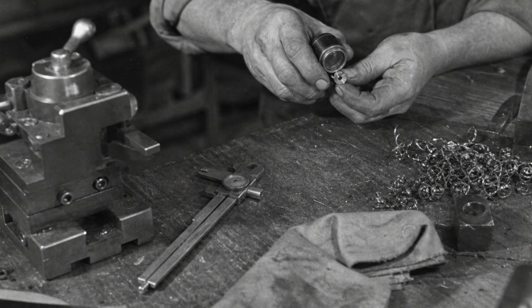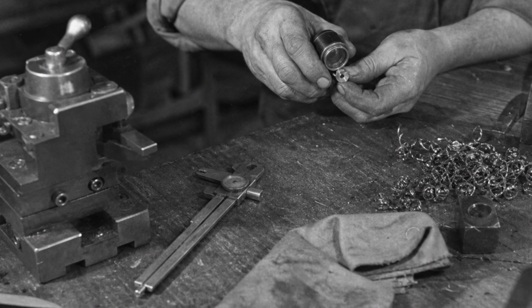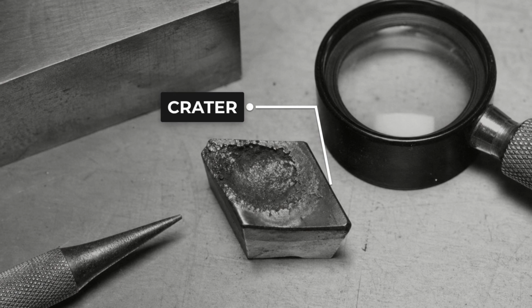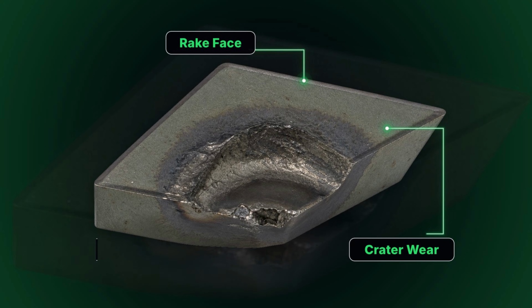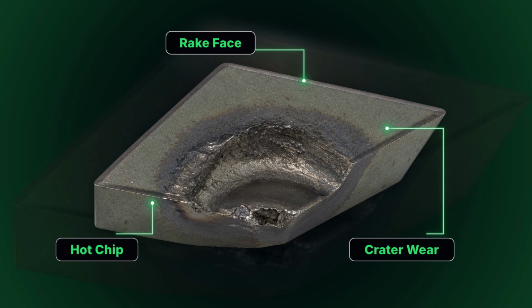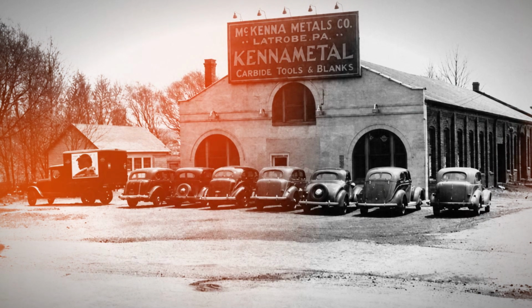Early carbide had a flaw every steel cutting shop found immediately: straight tungsten carbide craters in steel. The hot chip welds to the rake face and gouges a pit behind the edge until the lip collapses. The fix was chemistry, additions of titanium and tantalum carbide alloyed into the substrate, tantalum grades sold under names like Ramet, and one of the men behind it built an empire on the answer.